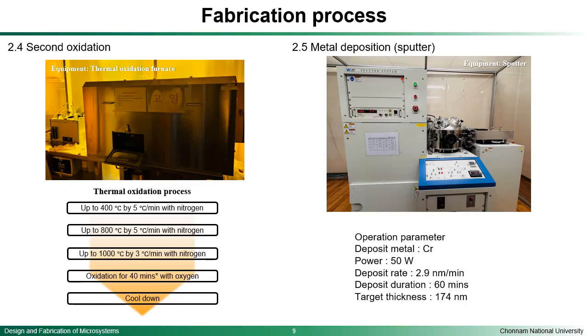Our target metal is chromium, and based on the sputter's power, we can determine the deposit rate is around 2.9 nanometers per minute. So this time, we just deposit for 1 hour, and the target thickness is around 174 nanometers.